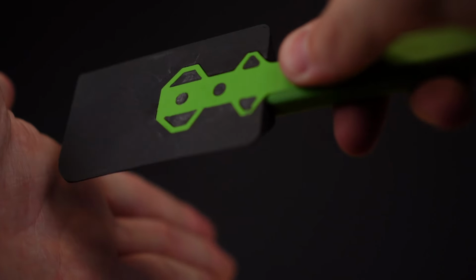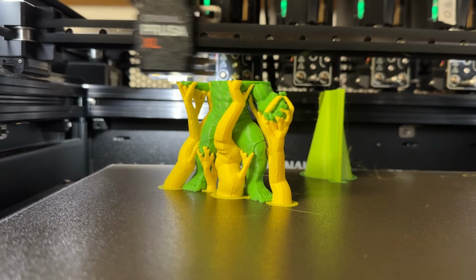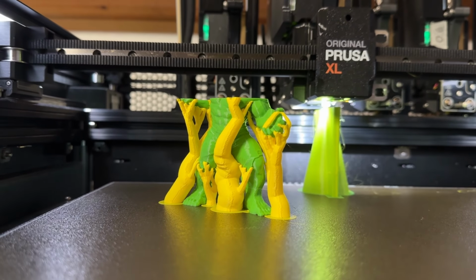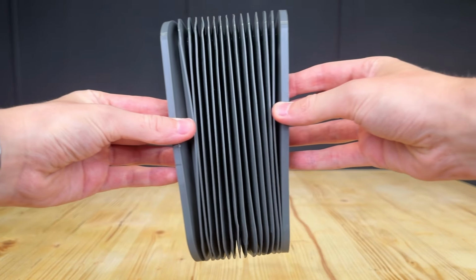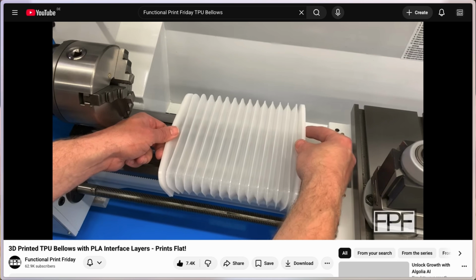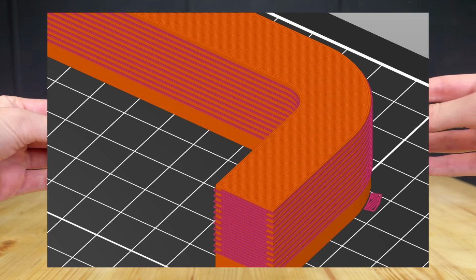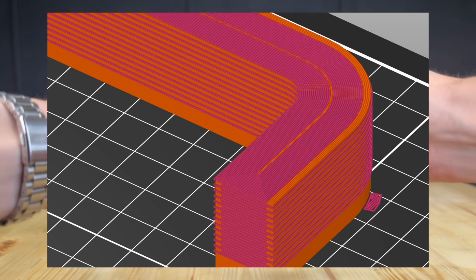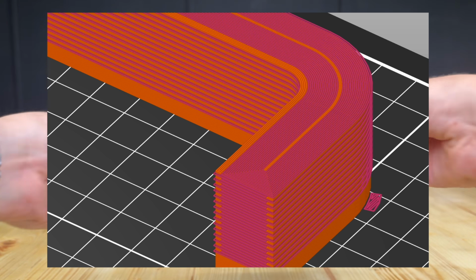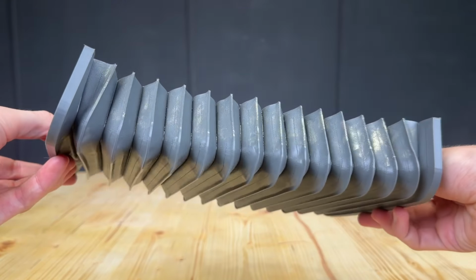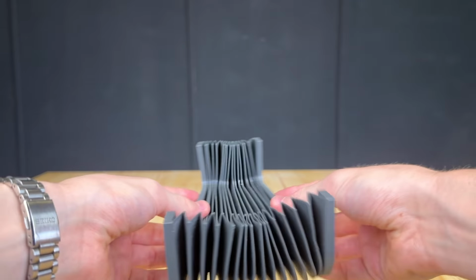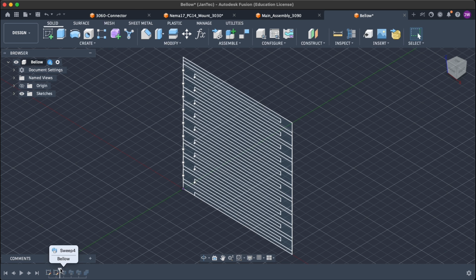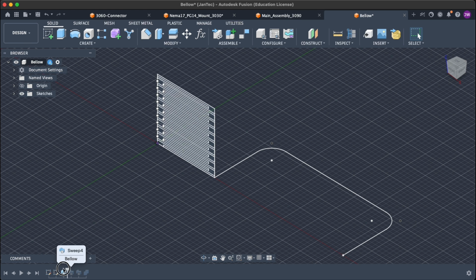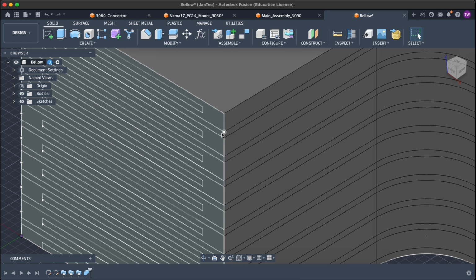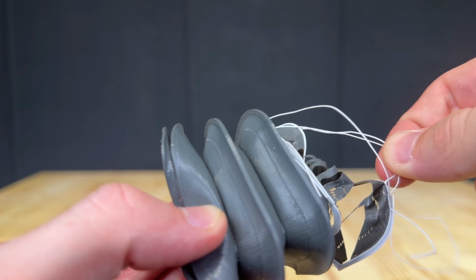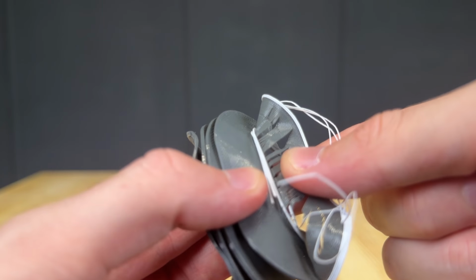Instead of only combining TPU with other materials, you can also use PLA as a support material for TPU prints, like for these printed bellows. Functional Print Friday has a clever method here, printing TPU and PLA in alternating layers, then peeling the PLA away to leave a clean folded bellows. Useful as a dust cover over a linear rail, for example. I printed one myself, and I've been designing my own smaller bellows for my universal testing machine. I haven't taken that as far as I'd like yet, but once they are fully parametric bellows, it opens up a huge range of applications.